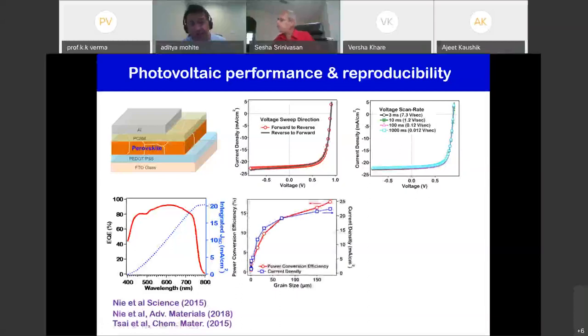And of course, you can plot your power conversion efficiency on the left as a function of grain size. As I said, as your casting temperature or your substrate temperature is increasing, your grain size is increasing. So you have this beautiful correlation where as your grain size increases, you see a very nicely correlated increase in your current density, which is plotted on your right, and also your power conversion efficiency.